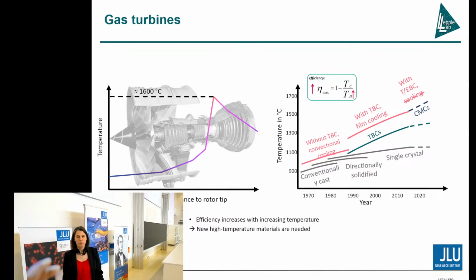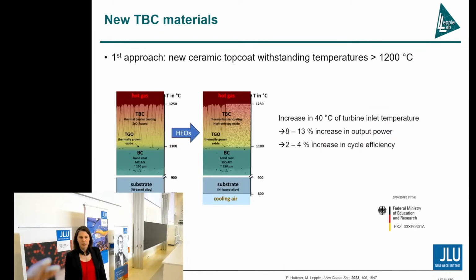However, we want to go further, and therefore we need new high temperature materials. So the first approach I want to show here is to find new ceramic top coat materials that can withstand temperatures above 1200 degrees centigrade. At the moment, 1200 degrees centigrade on the surface of such a turbine blade is the maximum temperature. There's a difference between the combustion temperature, which is around 1600, and the 1200 degrees centigrade, and this is achieved by active cooling.